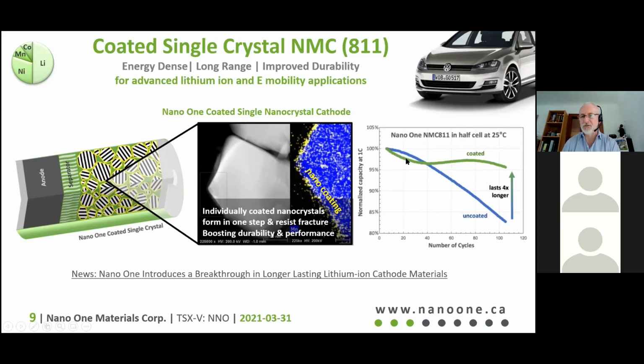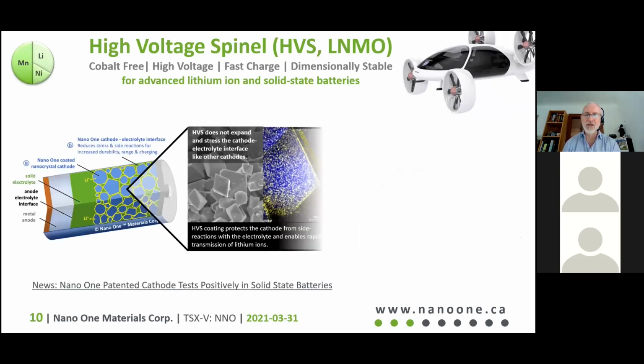Here we have an example of the same material made at Nano One without the coating. And when you add the coating, you get much greater durability and less degradation. We're taking this forward to scale up and to making full cells, so we can do some real durability testing with our partners and collaborators. The high voltage spinel, the LNMO, is the cobalt-free high voltage material, and it behaves in a very similar way.